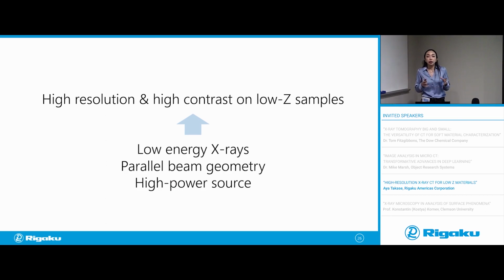But when you increase the resolution, your scan tends to take longer. The time is another thing you're compromising when you use high resolution. And you could get to the point that the scan could take 30, 40 hours. If you want to do it in a little bit more practical amount of time, you're going to need a high power X-ray source to do this. That's one of the reasons why you need it.